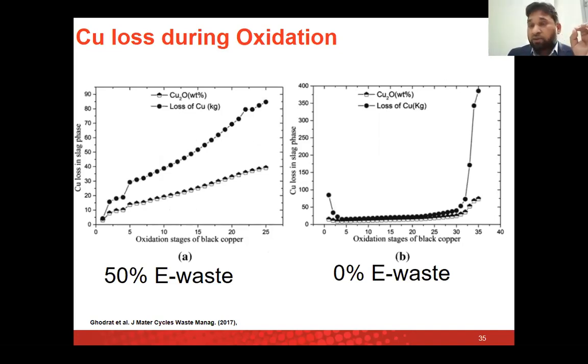So one of the major concerns in the oxidation stage is the loss of copper. The loss of copper is a concern that we need to consider, how much copper we are losing. Based on that, we have to optimize our process. We can see this when we are using electronic waste. So we need to tailor the conditions in such a way that we avoid the danger of losing copper in the form of copper oxide. This is a challenge we need to work out to improve the overall process itself, so that we have a minimum loss.